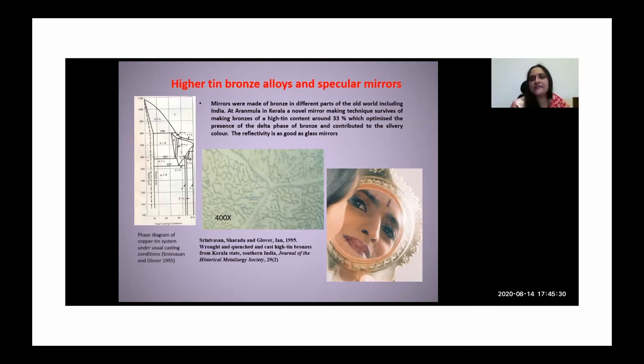So this phase that you're looking at, that silvery white phase, is all the delta phase. And there is a little bit of the bluish white alpha plus delta eutectoid. And this particular alloy has very high hardness, about 500 VPN or so. And because it's hard and because it's silvery, it takes a very good polish and it forms a good mirror.